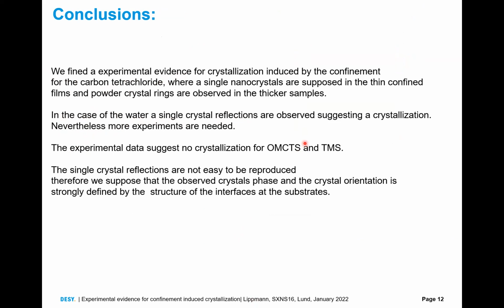In the case of OMCTS and TMS, we believe that there is no crystallization, since these two liquids solidify very fast, and this prevents the building of crystals in the gap. What I also want to say is that it is very difficult to repeat the single crystal reflections from one experiment to the other. That's why we suppose that the surface structure and morphology are very important and play a big role in this process.